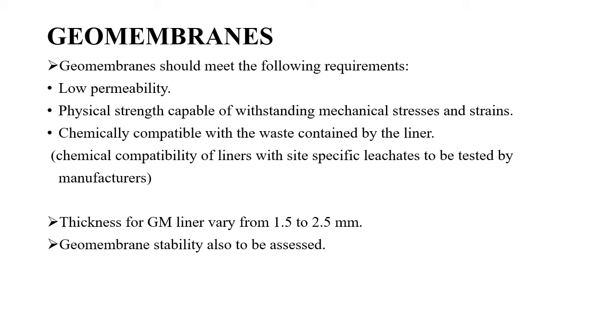Because if you're going to construct a municipal solid landfill, and for constructing the liner system you need a geomembrane, then you have to look into the leachate which is going to possibly be generated from this municipal solid landfill, and the chemical compatibility test for the geomembrane material should be done using that municipal solid landfill leachate. Only then will we be able to assess correctly whether this geomembrane which has been manufactured is chemically compatible with the site specific leachate or not.